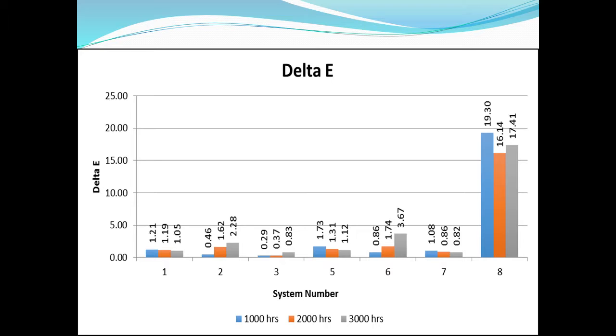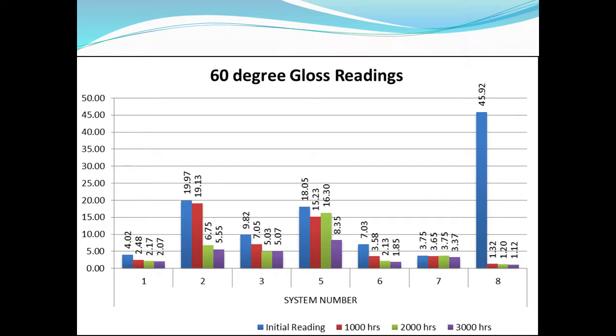The change in color, again, is an indication that something is going on with your coating. And all of these, the first 7 are pretty good. Not huge changes. But system 8, again, we had a huge change from its initial condition to the 1,000 hours and the 2,000 and 3,000 hours. So it changed a lot. Gloss reading, again, is an indication as your coating starts to break down, you're going to get down glossing typically. Again, system 8 performed pretty poorly, and the rest of them not so bad. System 2 had a bit of change, but even though system number 5 had a fair amount of change, it mostly started high. It looks like there's something going on there, but it didn't change as much as you might first think. So it didn't perform poorly in that.